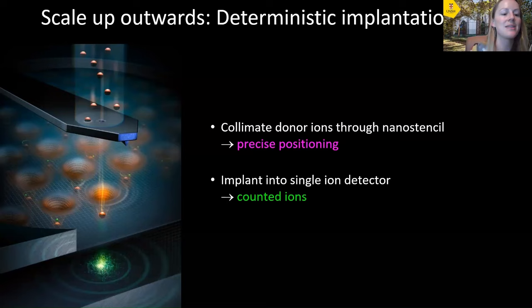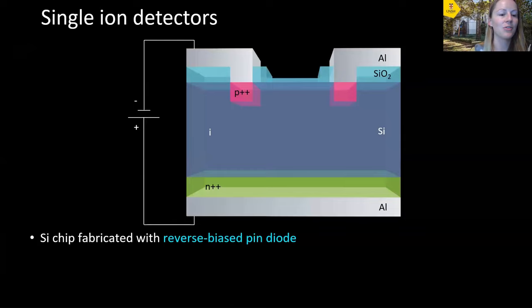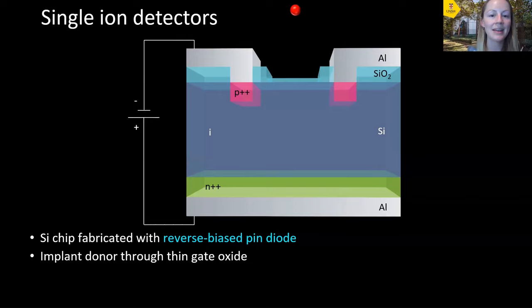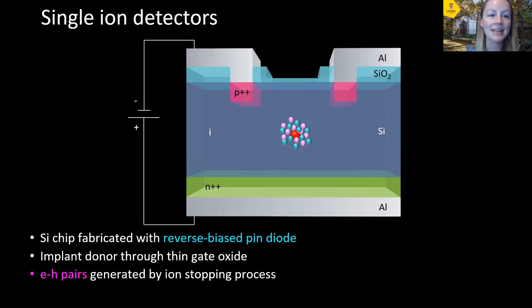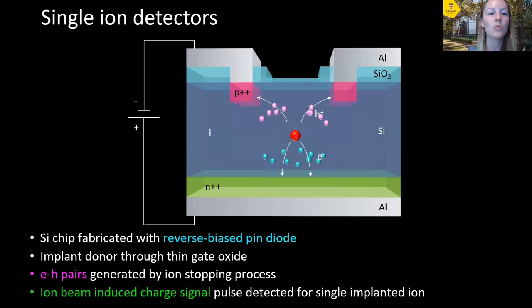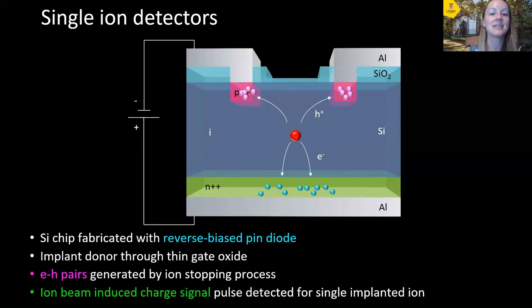So how do we realize these single ion detectors in our system? So we first have to fabricate a PIN diode on our silicon chip and apply a reverse bias to the electrodes at the top and the bottom of our silicon substrate. And this means that when you implant a donor ion into the detector's construction site that has a very thin gate oxide, then because we generate electron hole pairs in the silicon as the ion slows down, because we have this electric field gradient from the electrodes in the detector, these electrons and holes will be swept to opposite electrodes in the detector. And this will allow us to detect an ion beam induced charge signal for the implantation of a single ion.